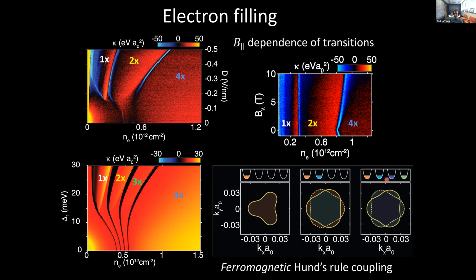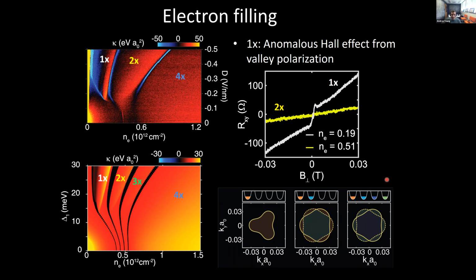And then the 4-fold phase is, of course, totally symmetric. Okay, so it's sort of a ferromagnetic Hund's rule coupling. And this is confirmed by measurements of the anomalous Hall effect, which is different in the two different valleys. So if you have a valley unpolarized state, as in this twofold state, you'll have no anomalous Hall effect, but in the valley polarized state, you will have an anomalous Hall effect, which indeed we observe.